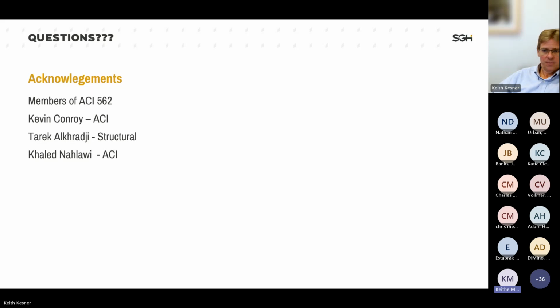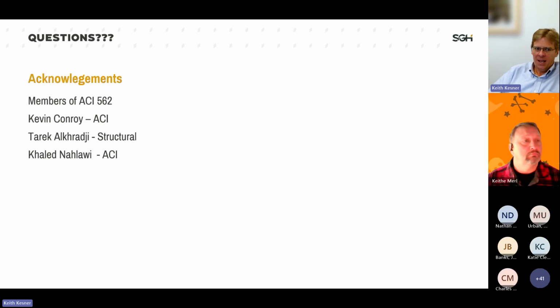So I don't see any in the Q&A, but I did have a question. Is there a way to coat or protect the externally bonded FRP to reduce the impacts of the extreme heat? I mean, there's not a good one. You do see some people putting cementitious coatings on top of the FRP. And the problem is if you have something externally bonded and exposed to fire, it just doesn't hold up. There are some epoxies that have better thermal performance, but it's not common. And really, once you get to a temperature of about, depending upon the epoxy, 180 or so degrees Fahrenheit, you start to see softening of the epoxy material, and you get into the glass transition temperature of the epoxy, which is when it starts to actually degrade.